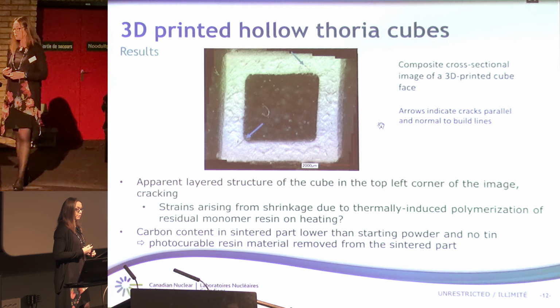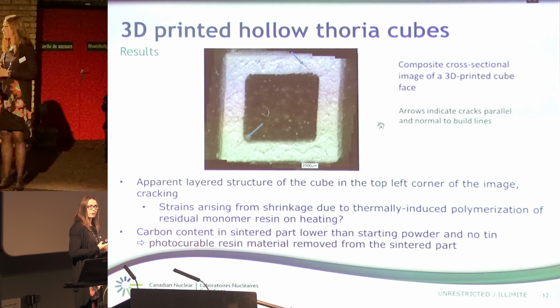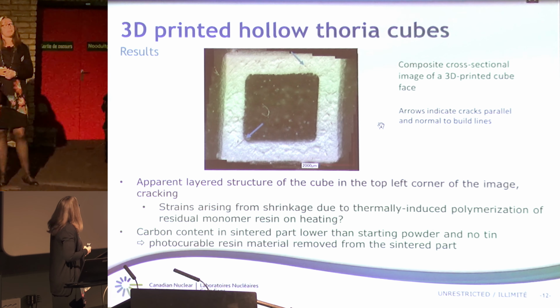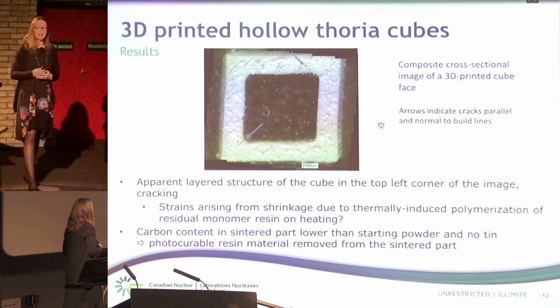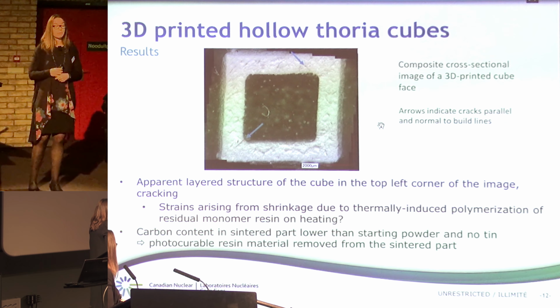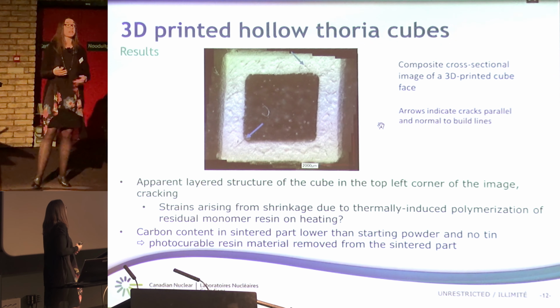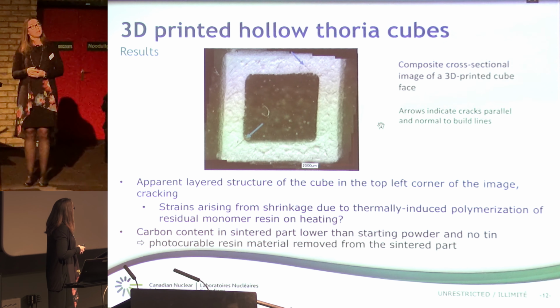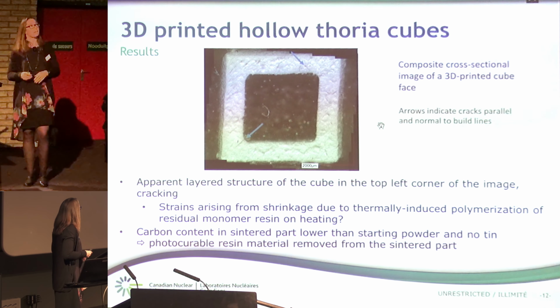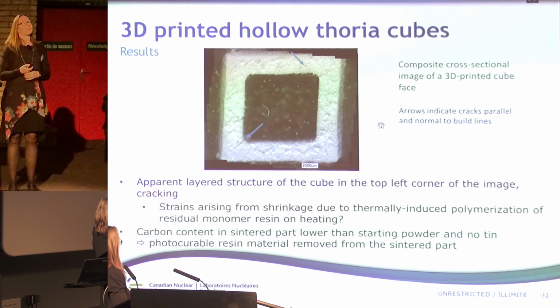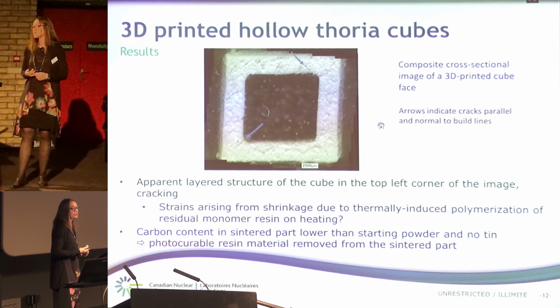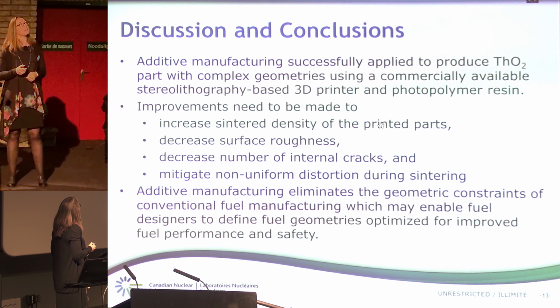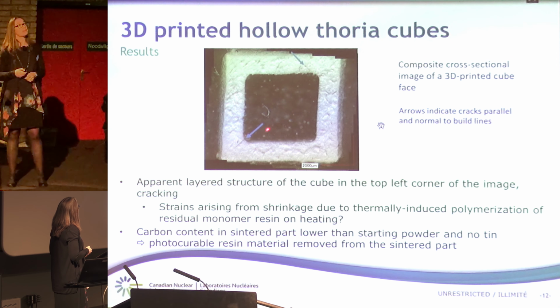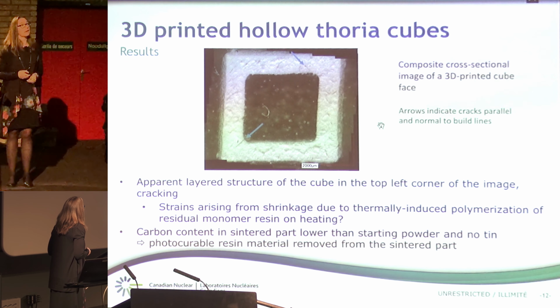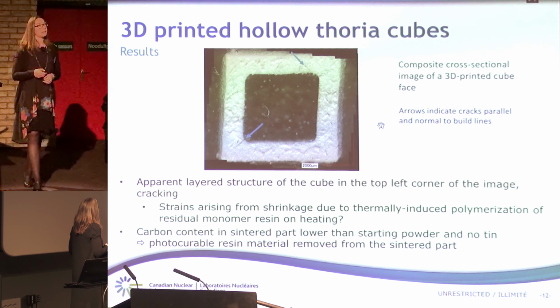When we wanted to know a bit more about the microstructure of the final parts, we examined those cubes after slicing along one of the faces, and after having put those parts in a resin, in epoxy, and polished and so on. And we did a composite cross-sectional image of the 3D printed cube face using some software to stitch the different images. What we observe is that there is an apparent layer structure of the cube, especially around here, and we can observe cracks also in parallel and normal directions compared to the build lines.